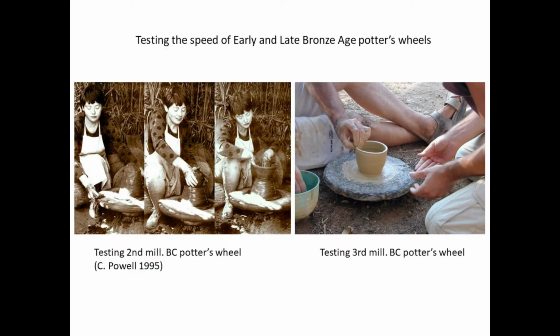As for the relationship between the wheel fashioning technique and the type of rotary instrument, it has been evoked in several papers. I want to recall that we can identify how rotary kinetic energy was used on the basis of ceramic surface features and microfabrics. However, identifying the type of wheel from the way rotary kinetic energy was used is far from obvious. When small pots are wheel thrown, it can be said that the wheel was revolving at a minimum of 100-120 rounds per minute, because this is the minimum speed required to throw small pots on the wheel, as shown by Catherine Powell's experiments and ours.